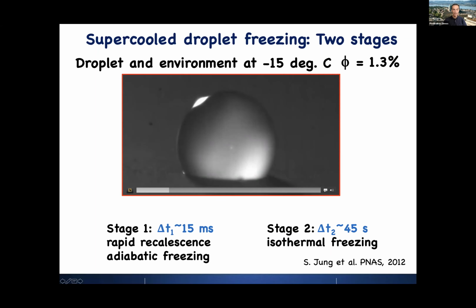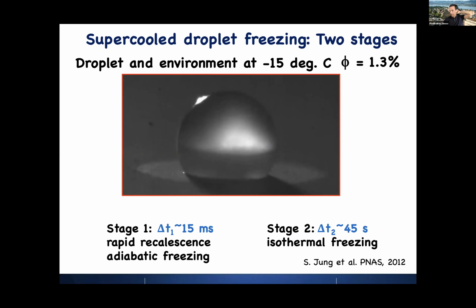And after which point, there is a second phase of freezing, the normal freezing. Now you have an isothermal freezing where everything is 0 and the freezing proceeds to the end. The first phase is adiabatic because this release of heat is so fast. So the time scales of heat diffusion for the heat to go away are much larger. So effectively, you have an adiabatic, very rapid phase, and then an isothermal classical phase, or more classical, that lasts about 1,000 times longer. Okay, so this is sort of the story of cooling.